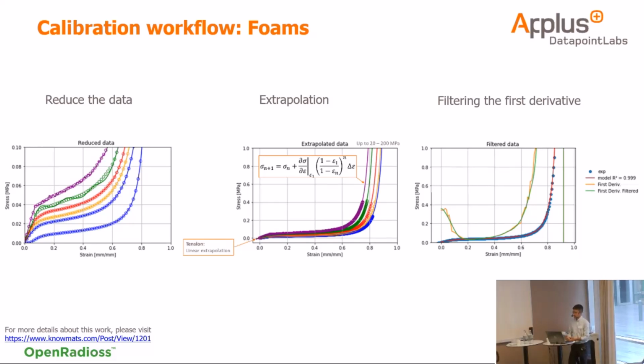And then once we have this extrapolated curve, we filter the first derivative. This step, which was suggested by Marian, is really the key to guarantee the stability of the model. As you can see, the yellow curve is the first derivative of the curve. You can see a bunch of noise and sharp edges. And then when you take the first derivative, you can filter it and smooth it out.